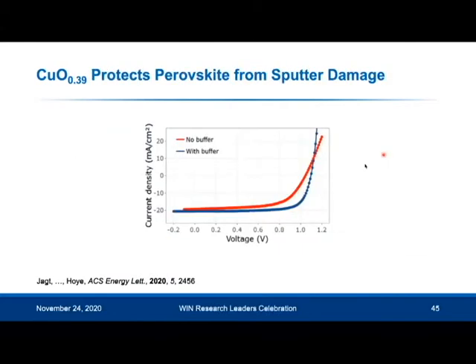So this red curve is the IV curve for our perovskite devices with ITO sputtered without any cuprous oxide, and the blue curve is with cuprous oxide.